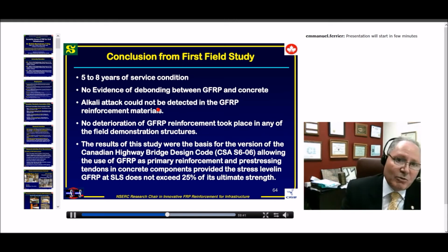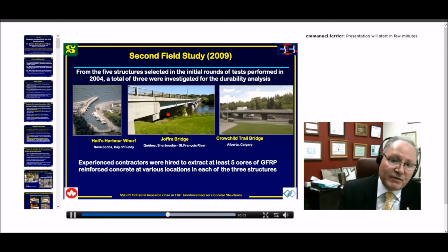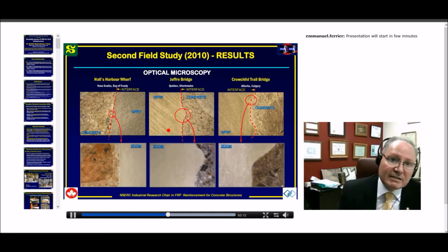And we decided, as I'm saying here, to introduce the GFRP as main primary reinforcement in bridge components, but limiting the stress to a maximum of 25%. And from this time, we did another field durability study in 2009, bringing the structures to 13 years, and we have almost the same results as you can see in this next slide.